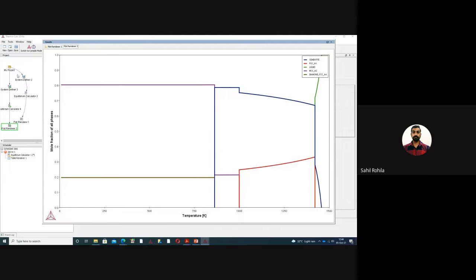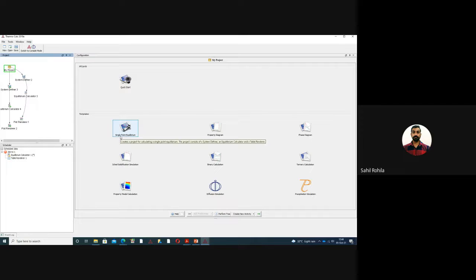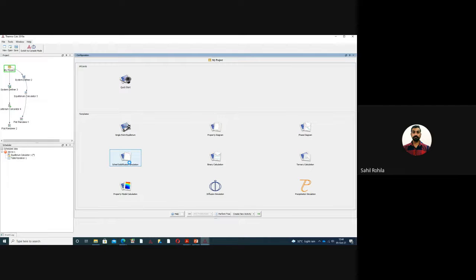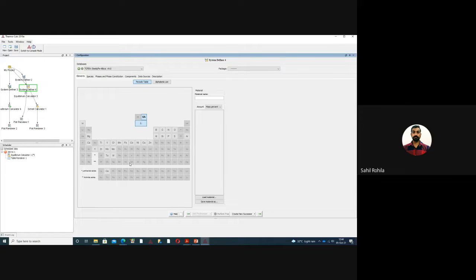And this is how we can obtain the data of phases of a particular fixed composition with respect to temperature. So the modules that we have covered today are single point equilibrium, property diagram, phase diagram, binary and ternary calculations. The other modules are solidification, where we get the solidification curve, diffusion simulation, and precipitation simulation. Scheil solidification I can also show you within a minute. Scheil solidification uses the same assumptions as the Scheil equation and the solidification equation used for solute redistribution. The assumptions are that there is no diffusion in the solid phase, and infinitely fast diffusion in the liquid phase.